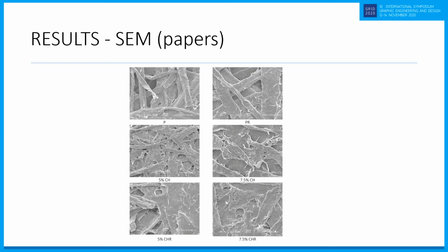With the scanning electron microscope, the distribution of chitosan and rye starch on the paper sheets has been evaluated. You can see all the images here. These micrographs show that the fillers covered the fibers and closed the pores, and at the same time the open areas in the base paper.